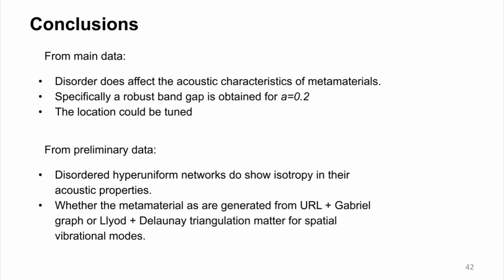So to conclude, what did I find out through these studies? I found out that disorder does form a tuning parameter. It does control acoustic properties, and around disorder of 0.2, I do actually find a band gap, and the band gap is robust under multiple different tensions that I've tried. I also propose that the location of the band gap could be tuned by changing the interpoint spacing of the original point distribution.